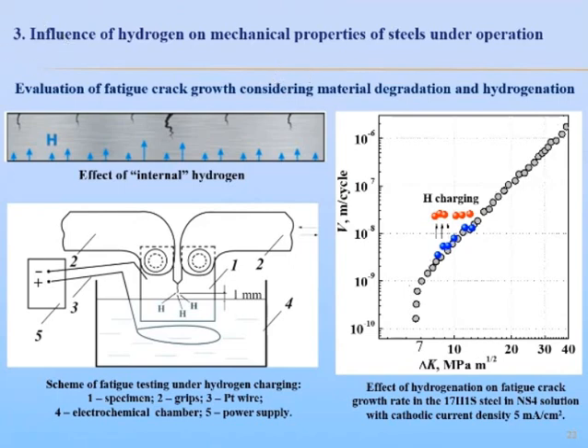Fatigue growth in steels is usually studied under conditions of filling the crack cavity by a hydrogenated environment. However, in this case, to study the effect of internal hydrogen, a special scheme of fatigue testing and hydrogen electrochemical charging has been developed.